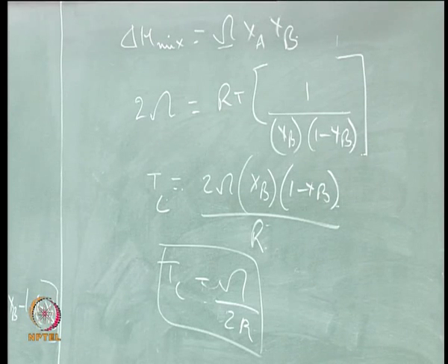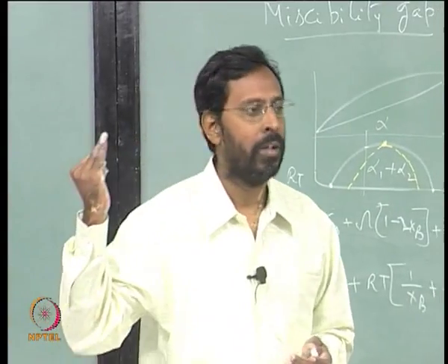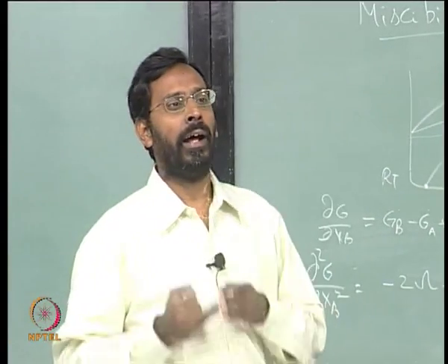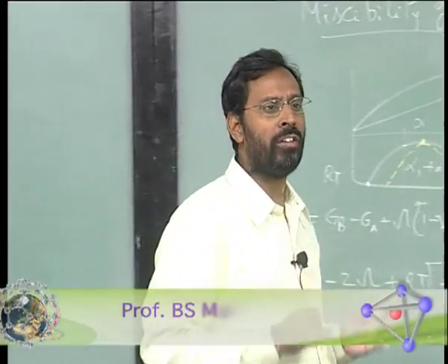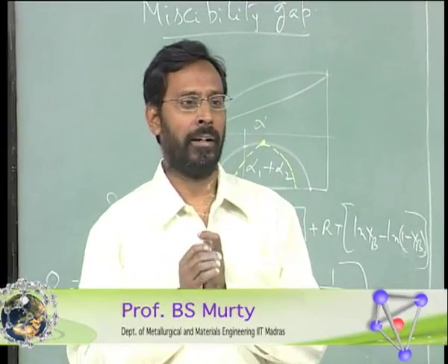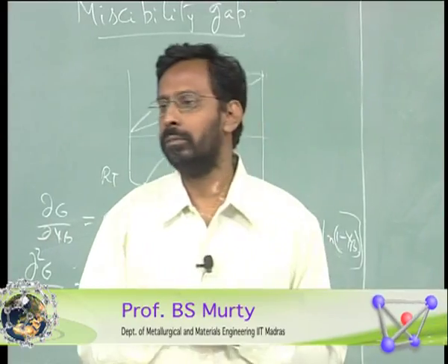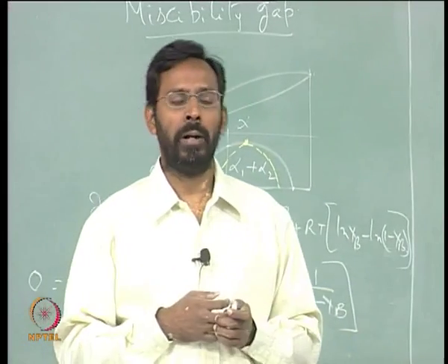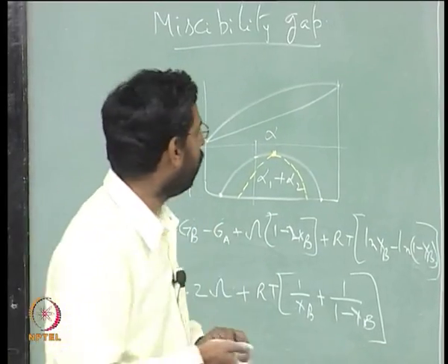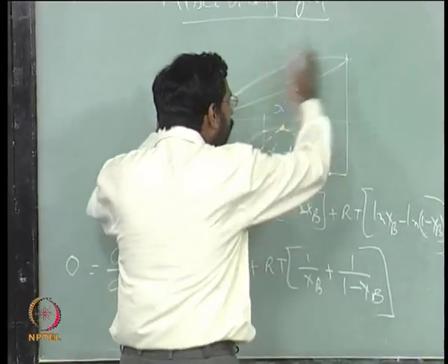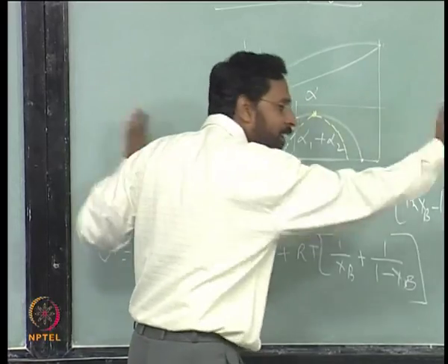Regular solution model, and one more assumption. Yeah, we are assuming that the spinodal or the miscibility gap closes at the middle of the phase diagram. It is an assumption. It need not, but in a number of cases you see that, provided your phase diagram is a simple isomorphous and there is nothing else on the other sides.